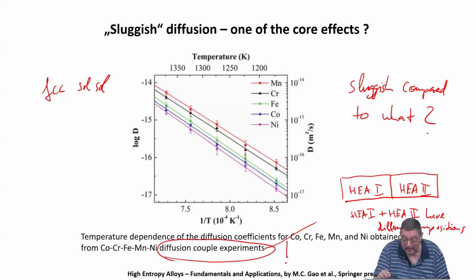But here you see the nice thing about the Cantor alloy is we have several elements in there which are not FCC, but the whole thing at sufficiently high temperatures is completely FCC. But at room temperature, different. At a high temperature means maybe what? This range here, right? I mean, above something like 950 Kelvin or so, the solid solution phase is stable at equimolar composition.